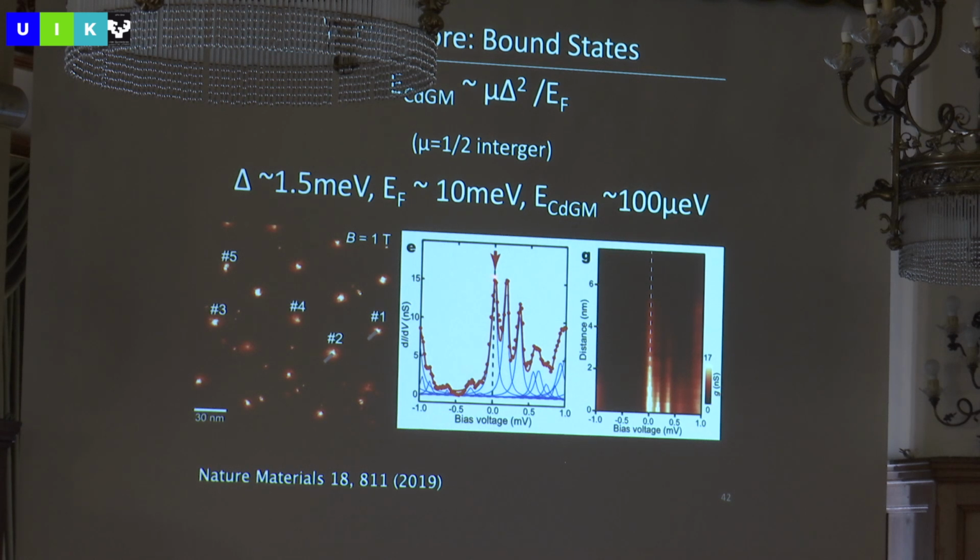So they can see the difference between something at 0 and something at 100. And they were able to show that within their resolution of, let's say, 30 microvolts or something, this zero bias peak is exactly at 0. Okay? By the way, the resolution tells you whether you're able to distinguish two peaks separated by that amount. This thing being at 0 is even better than that resolution.